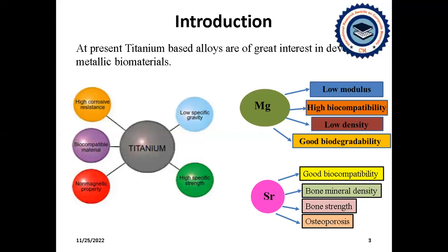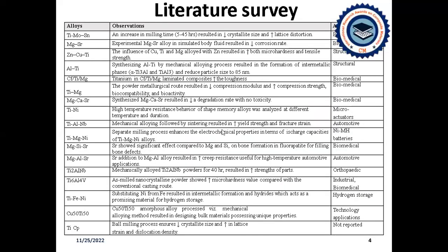The addition of strontium and magnesium to the titanium alloy will not only increase biocompatibility, it also helps in the corrosion resistance and the degradation, and it slows down the rate of degradation. Therefore, the possible application of the ternary titanium, magnesium, strontium alloy with high strength and low density as biomaterials is attractive. Hence, this investigation is carried out in developing the Ti-Mg-Sr ternary alloy with the high energy ball milling process for biomedical application.